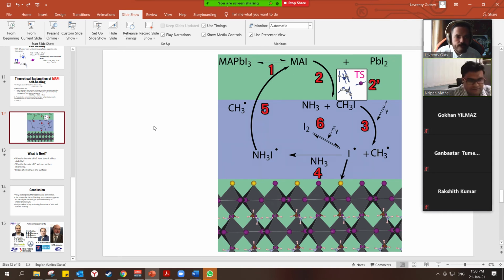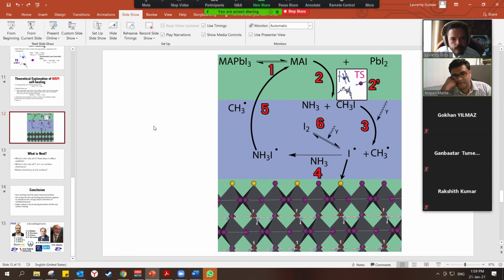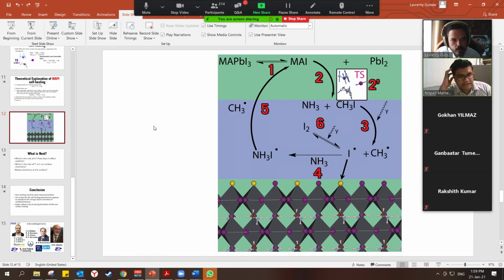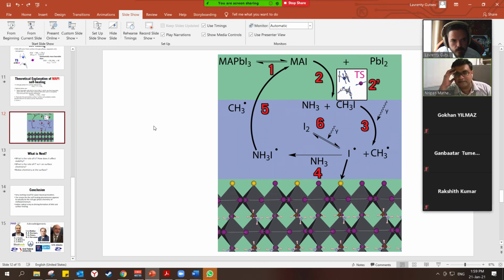Lavrenty, I had one question. Over here, this mechanism is to explain the self-healing phenomena in MAPbI3 when you look at the gamma ray results, right? But do you not think that this reformation can actually distort the lattice and therefore, although the material itself may eventually recover, the solar cell efficiencies may not recover because all these reactions would have interfacial reactions with whatever material is sitting on top of it? And I still have difficulty linking it to gas phase when the perovskite is a buried layer inside the solar cell.